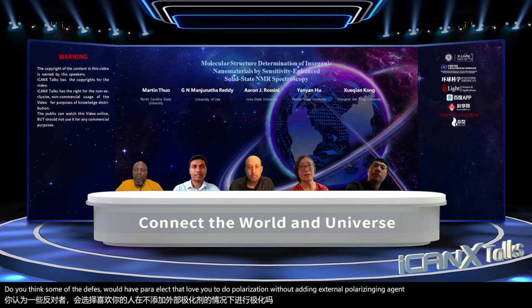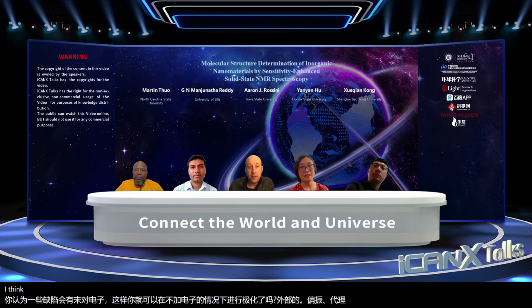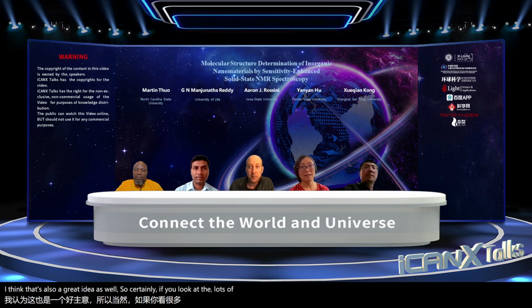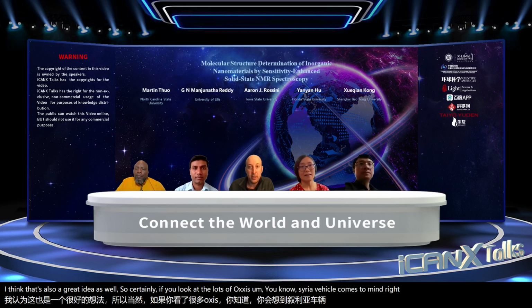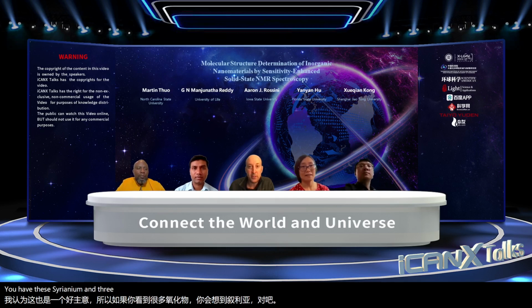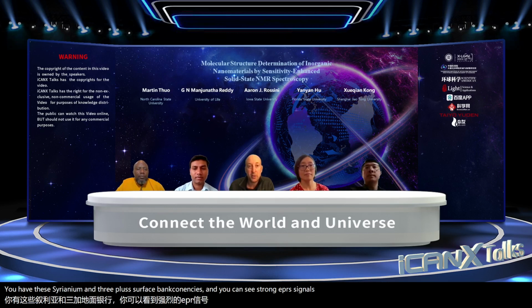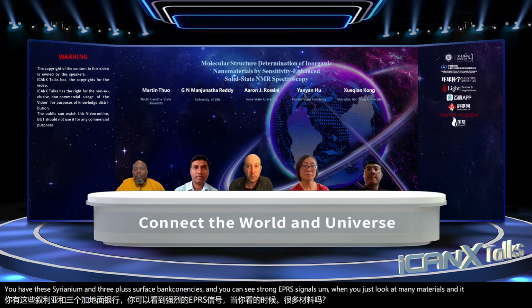Yeah, I think that's also a great idea as well. So certainly if you look at lots of oxides, ceria comes to mind, right? You have these cerium 3+ surface vacancies, and you can see strong EPR signals when you just look at many materials, and it's because of those dangling bonds on the surfaces.